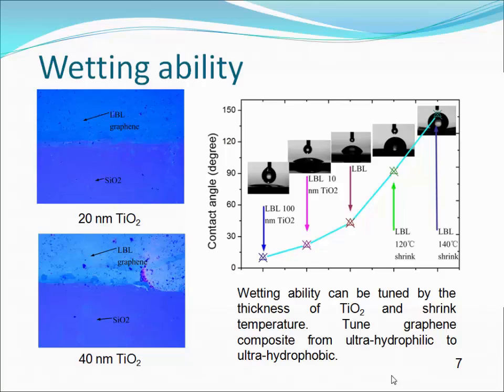And after the heat shrink, you can see that the water contact angle increases dramatically because of those nanostructures. So the wettability of these new graphene composites can be tuned by the thickness of titanium oxide layer and the shrink temperature. And we can tune the graphene composites from hydrophilic to hydrophobic.